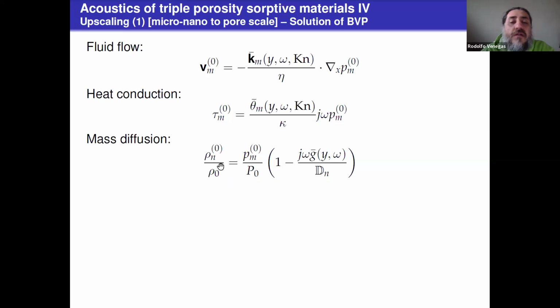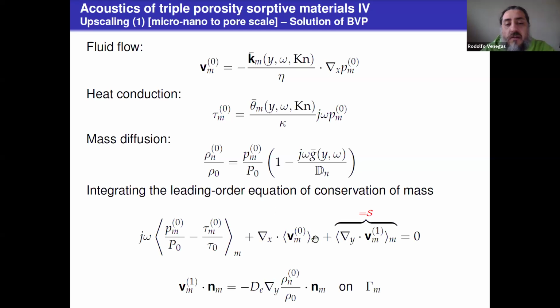And this can be thought of as an equation of state, where this term shows that the response of the media is not automatic, it's not instantaneous. There is a lag in time, a characteristic relaxation time working here, meaning that this will represent another way of dissipating some energy. So then we identify from the equation of conservation of mass the macroscopic description.